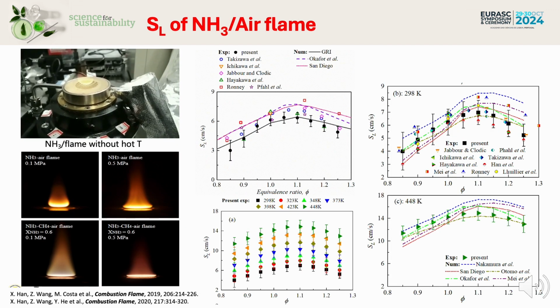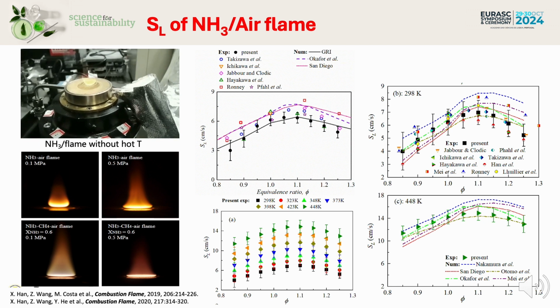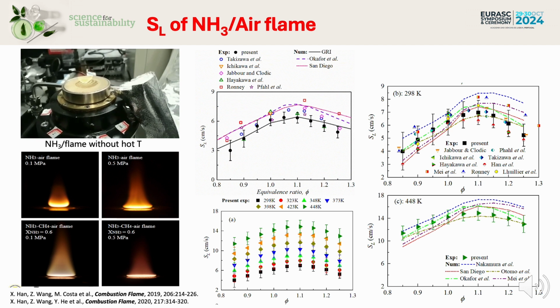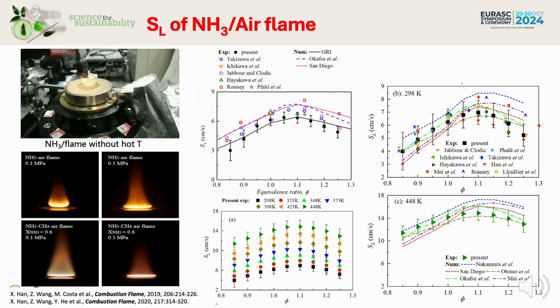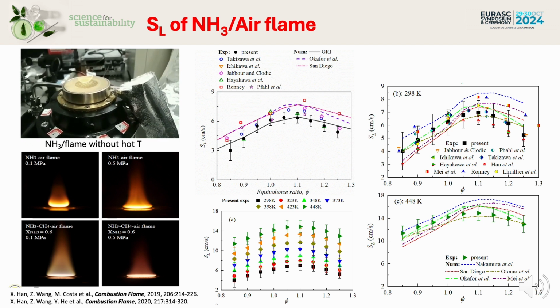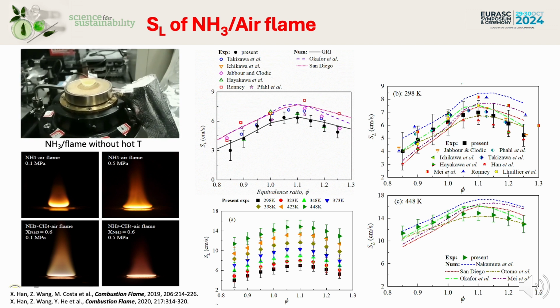So you can see that with the high-pressure rig and the updated heat flux burner, we can obtain very good experimental data for ammonia-air flames. The peak laminar burning velocity of ammonia is quite low, just 7 centimeters per second. But natural gas can reach 37 to 38 centimeters per second. Hydrogen can reach 280. That's quite a difference.